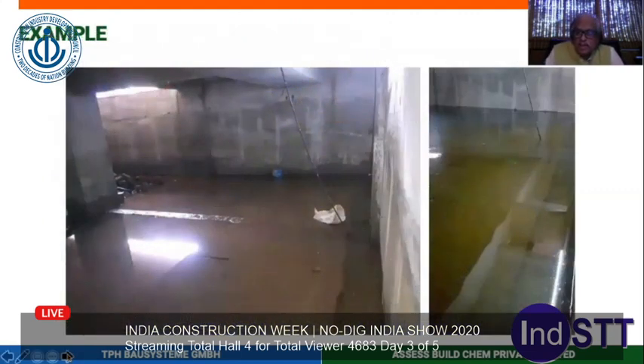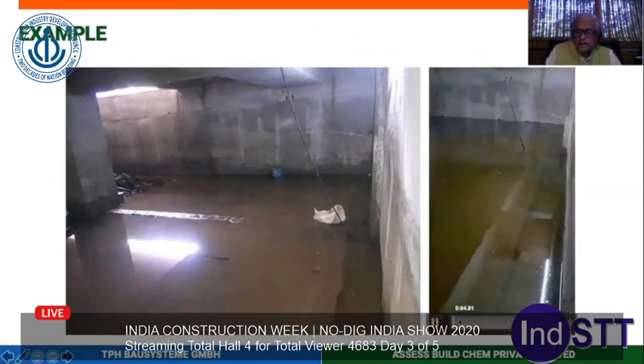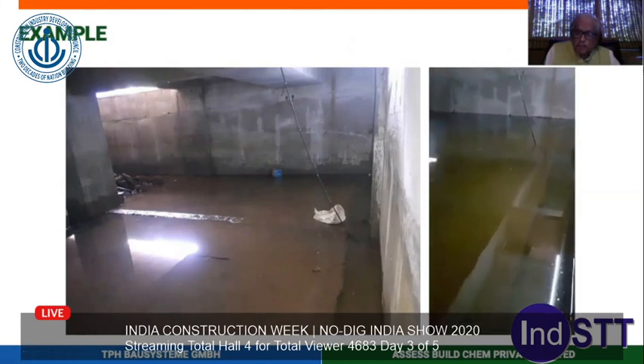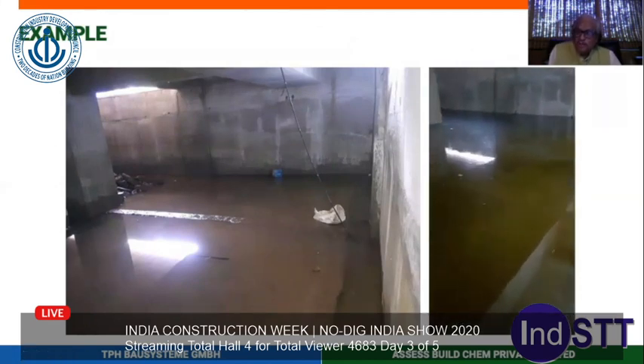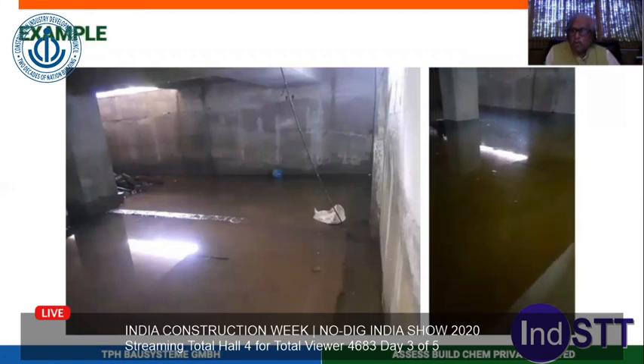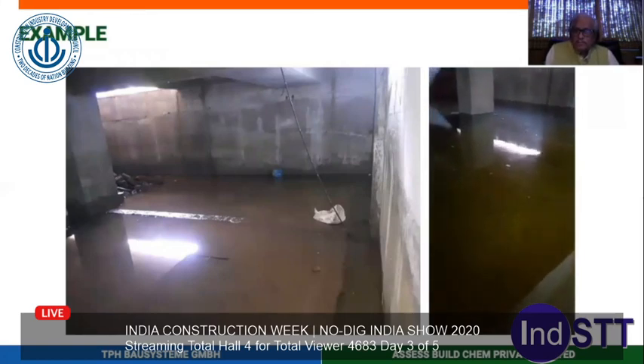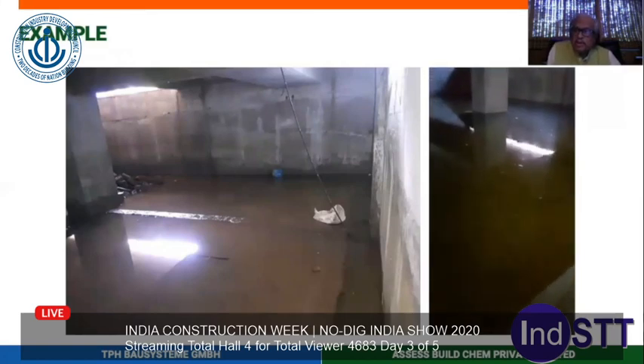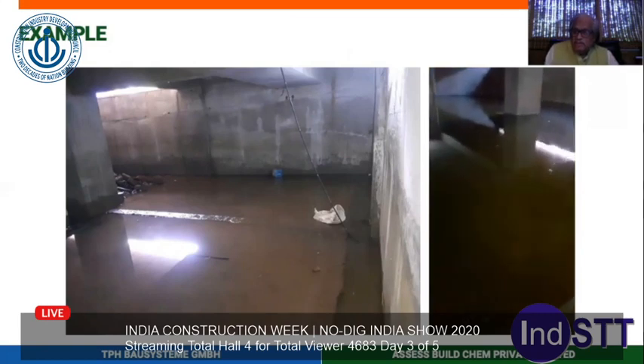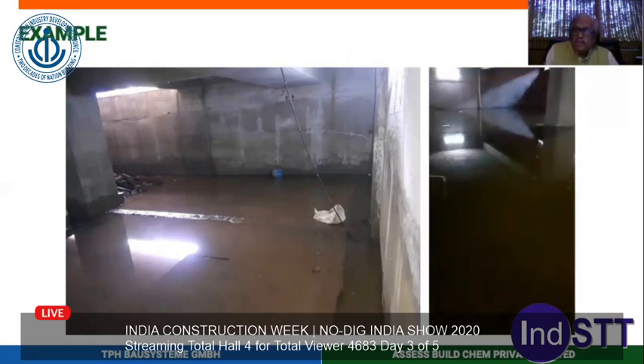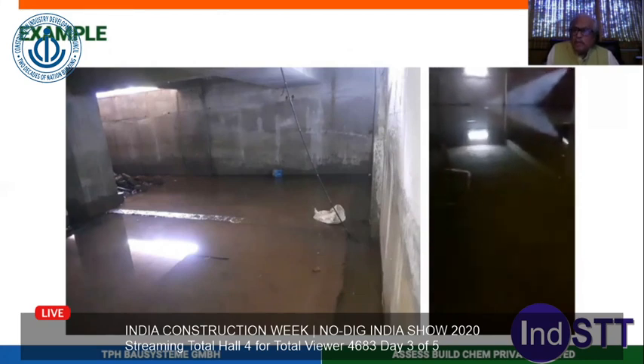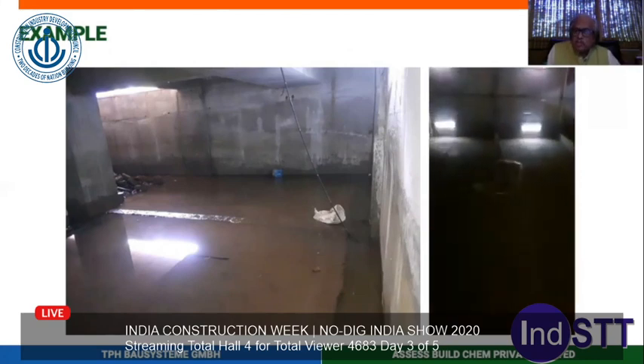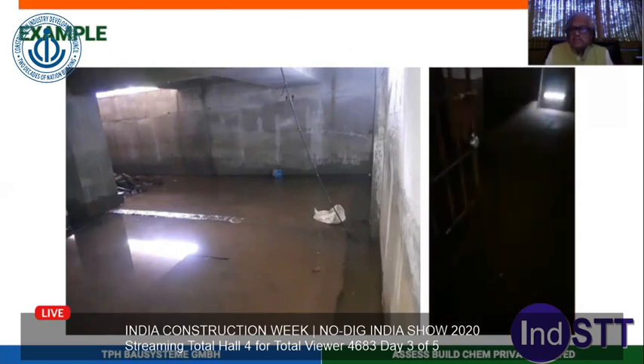This can be similarly used in our basements. We are having a lot of problems in our basements. The water comes inside and you cannot stop it by foam. If you stop it by foam, tomorrow, once the foam is thrown out, the foam is not durable. These materials are tested for durability of 100 years. There are long-term tests done in the field of about 20 years, and then by extrapolating, these materials are very suitable and remain almost permanently, which is very, very important.